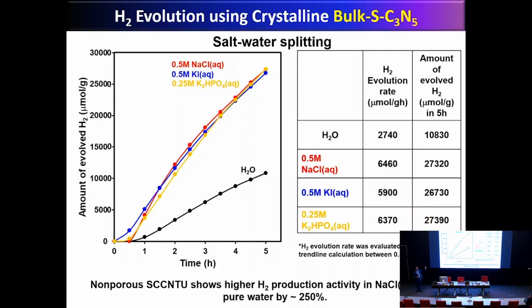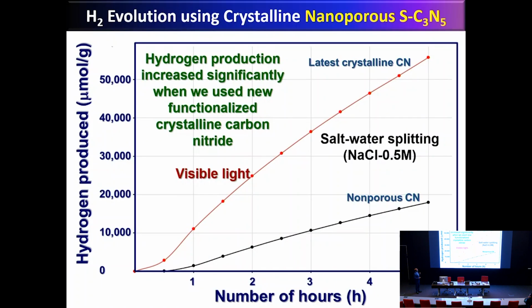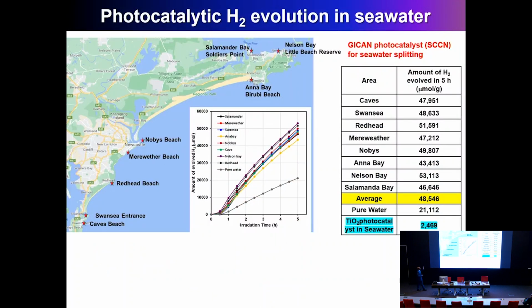This is bulk carbon nitride with a surface area less than 10 meters squared per gram. And when we use mesoporous carbon nitride with a sulfur-doped system, with the C₃N₅ with a crystalline framework, the performance increased to almost 50,000 micromole. And this is champion data in the world, and this is visible light for the carbon nitride. This is visible light seawater splitting. And we tested the material with the water collected from different beaches. So it's a groundbreaking discovery, and this was the dream of every researcher in the world, to convert seawater into hydrogen under visible light. So we have achieved it in our center.